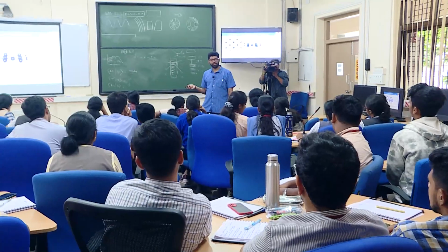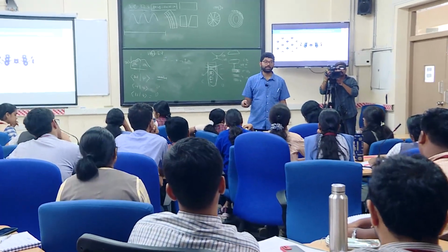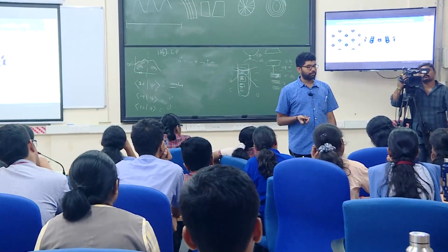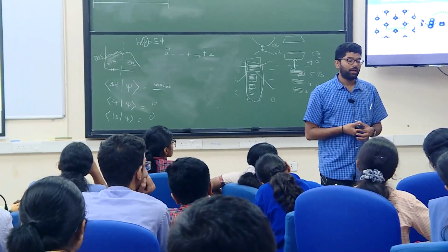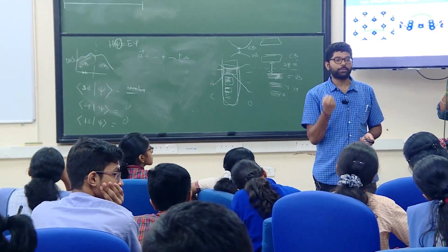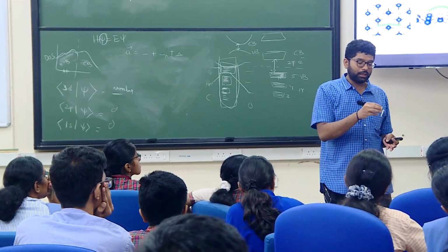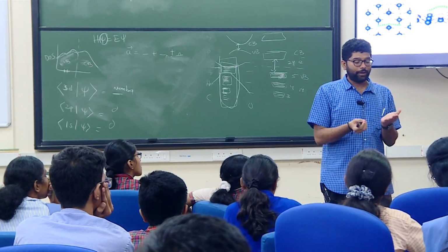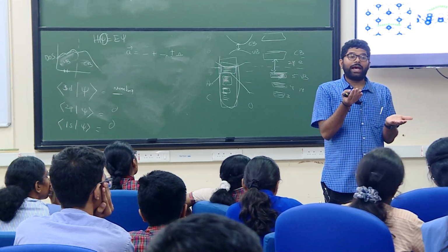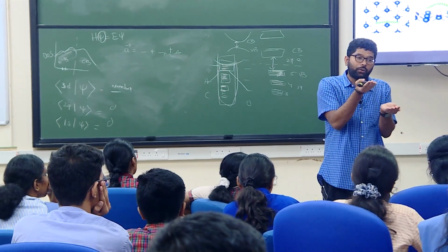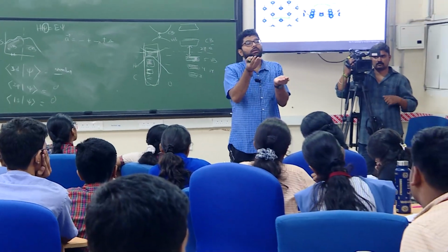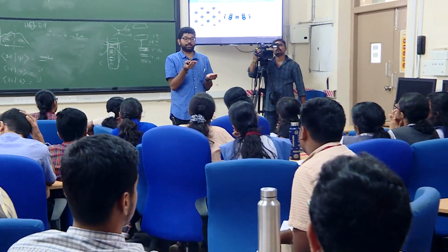So I told you earlier that among the 3 atoms, potassium, sodium and lithium, potassium has the highest adsorption energy and it has the least migration energy barrier. The reason for this is not about how strongly it is binding. It's about the overall structure. If I am having 3 sites, and the energy difference between site 1 and site 2 is very little, then the migration energy barrier will be less.